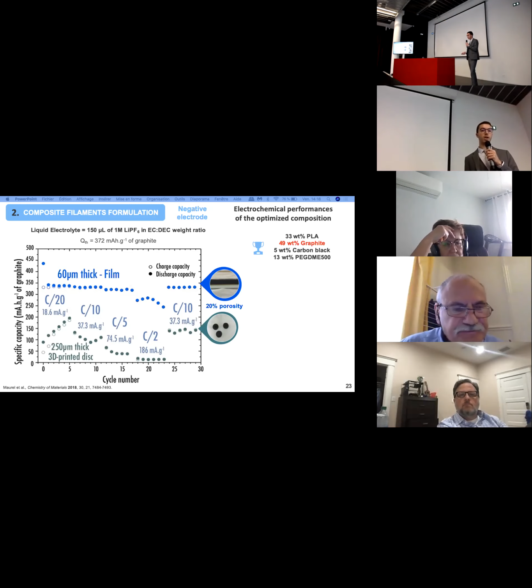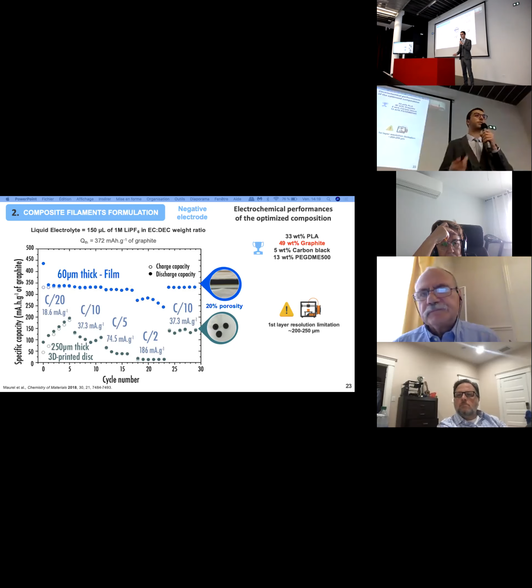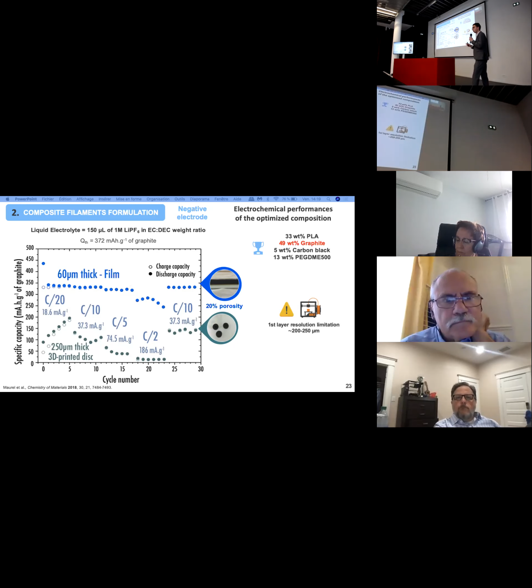And so here, for the exact same composition, you can see that we have a huge gap between what we obtained for the films and what we obtained for the 3D printed discs. Unfortunately, this gap is mainly due, and only due, I would say, to the difference in thickness. Indeed, with fused deposition modeling, you are subjected to a first layer resolution limitation. The first layer, when you print, will always be thicker, about 200, 250 microns, while for the upper layers you could go down to 50 microns. So we got this gap, but this is only due to this first layer resolution limitation.